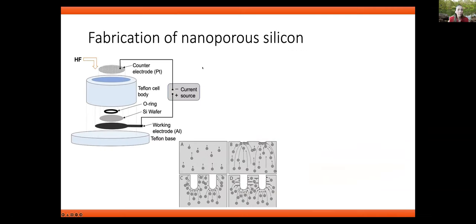We first needed to fabricate the nanoporous membrane. We used nanoporous silicon and electrochemical etching to produce nanopores. In this process, we have a silicon wafer, we put an O-ring and put it inside the cell, and we have a counter electrode of platinum here. We add hydrofluoric acid solution with some ethanol, and then we apply a current, so we effectively force the current to flow through the system. Normally we use P-type silicon, so the hole formation effectively begins at the impurities on the surface. Those are random impurities that then start etching, and then we etch deeper and deeper.